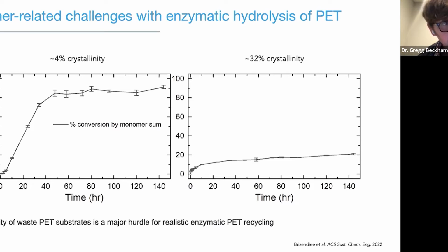And so PET in single-use beverage bottles tends to be on the order of 30% crystallinity. In textiles and carpets, it's on the order of 40% crystallinity, roughly. And in thermoforms and food packaging, it tends to be on the order of less than 10%. And what's shown here, this is enzymatic hydrolysis experiments in a pH-controlled bioreactor. These are all done at the 1.5 liter scale with that leaf compost cutinase enzyme that was engineered by Carbios and published in Nature in 2020.